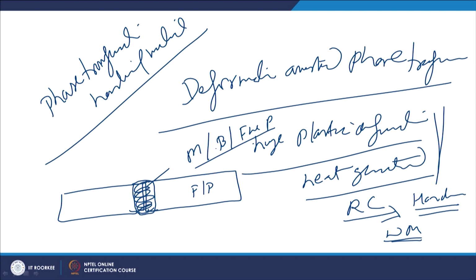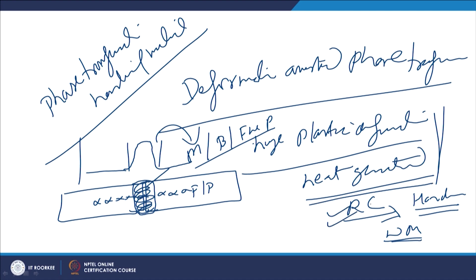And if we check the hardness distribution across the weld interface, we will notice that the base hardness is low, but as soon as we come across the weld zone, the hardness increases suddenly and then again comes down. This increase in hardness is attributed to the formation of martensite, bainite and fine pearlite due to the plastic deformation and the related heat generation followed by rapid cooling. Processes like explosive welding, friction welding and friction stir welding will all lead to property variation in this way.